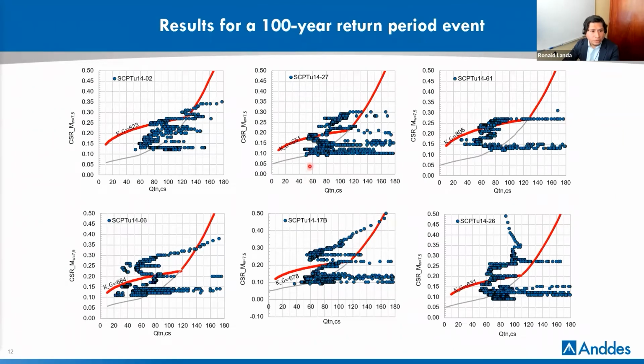Here are the results for a 100-year return period event. The procedure proposed by Robertson has been considered to include the estimation of the CRR for clay-like soils, which are the fine laminated layers in the delineation of heap leaching, composed of fine-grained ore, for the calculation of the equivalent CRR for a moment magnitude of 7.5. This depicts that the ore layers will not trigger flow liquefaction for a QTNCS lower than 70, nor cyclic liquefaction, which can be expected between 70 and 120 in value. These layers are greater than those that would liquefy if the ore were a soil with no microstructure, because the curve shown in gray is the standard liquefaction triggering curve.